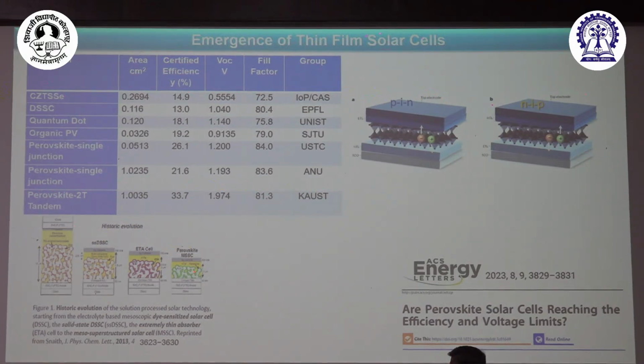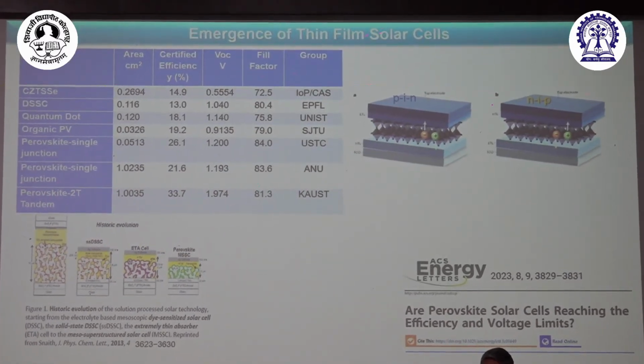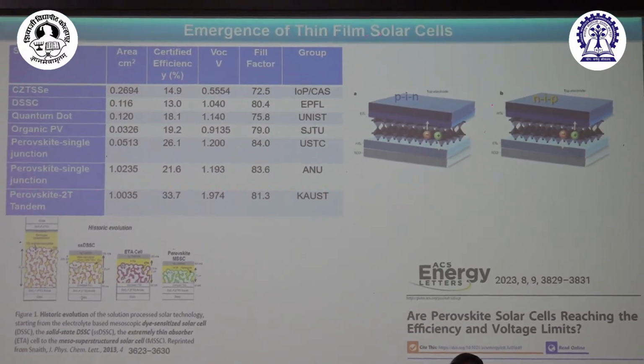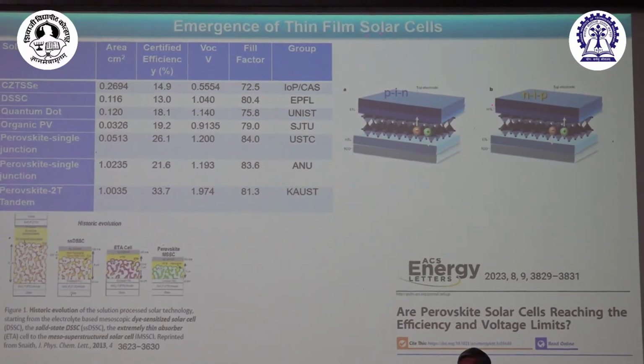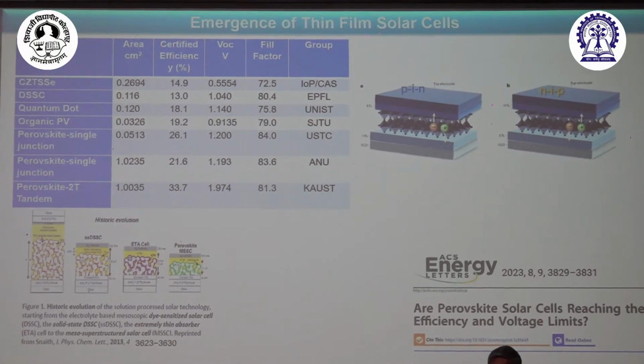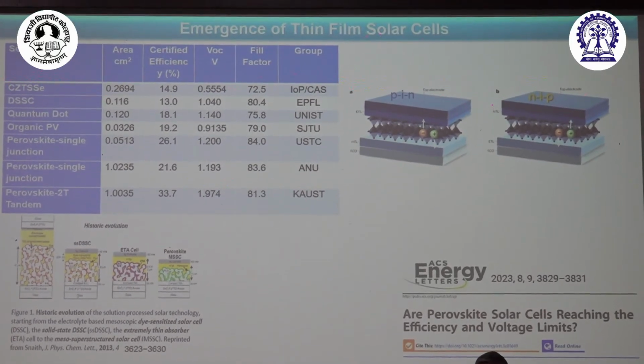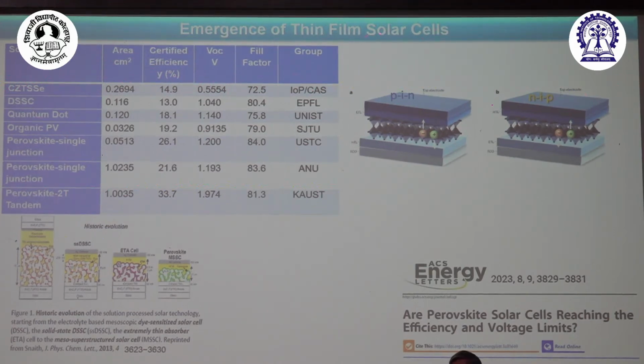As you can see here, over the period, the thickness started dropping, and the perovskite solar cells are less than a micron thick. Again, Professor Patil mentioned the silicon wafers are typically like 10 microns. So it gives you less material used for the solar cell. And these are the certified efficiencies. That means in the lab you make a cell, you send it to an independent party, they measure it. So it's not what you measured in your lab; they measured it, they calculate the area of the cell, they get the power output, and you know how much photon you're putting in, one sun. One sun is typically 100 milliwatt per centimeter square. And you take your solar cell under the same condition. If you take a 1 centimeter square cell and you get 10 milliwatt out of it, right? That means your cell is 10%.